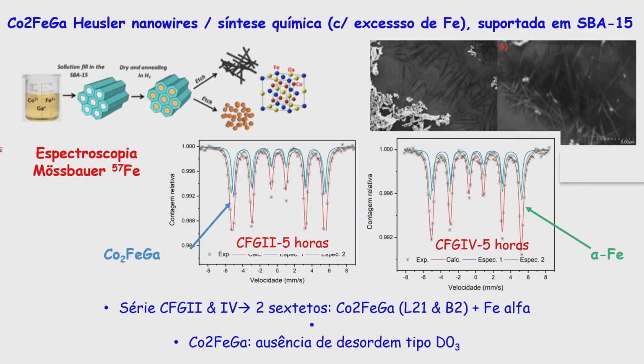I will skip that. Due to the pandemic, we stopped this kind of work. We are only working on nanoparticles. It was a final comment. My student was working last year on getting cobalt-2 iron gallium Heusler nanowires. Our idea was just to get nanowires to use them to do physics in a single nanowire, because these cobalt Heusler alloys are 100% spin polarized in theory. That means it is very interesting for a spintronics device. He wanted to use a recipe that is in the literature to get nanowires and use the nanowires to do physics.